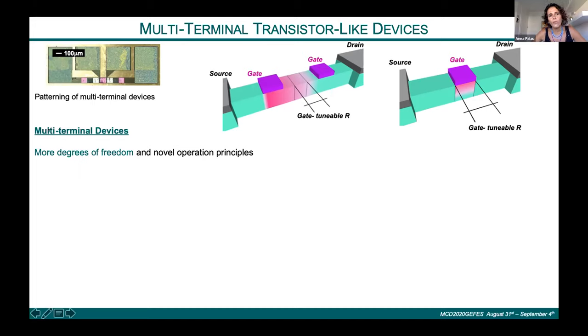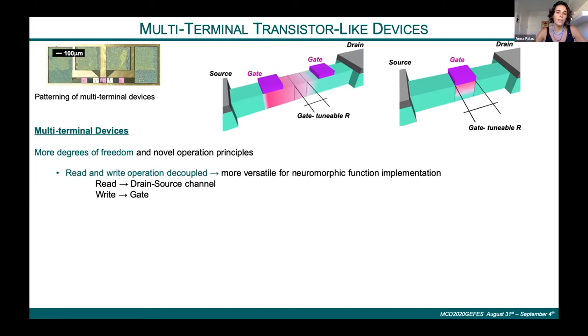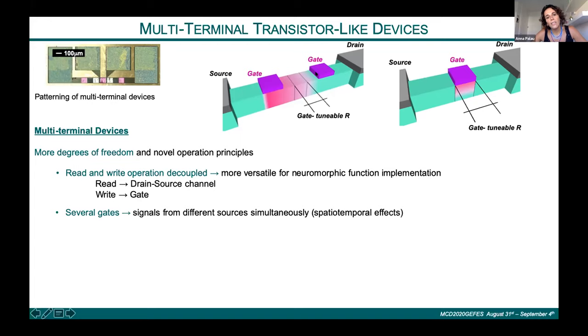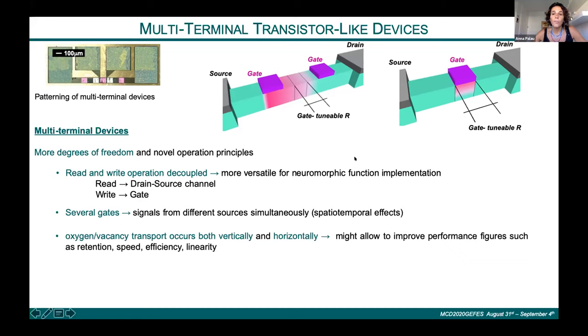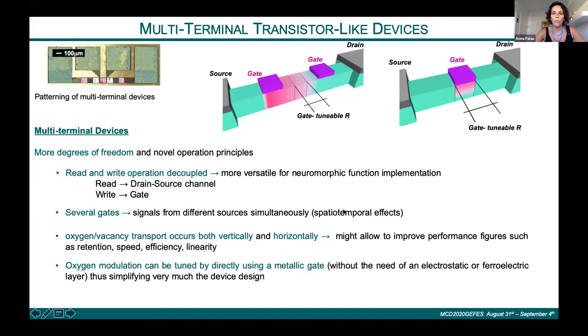By using these multi-terminal devices, we have more degrees of freedom in order to design these devices. For example, we can decouple the read and write operations in these materials. We can use the drain-source to read the state, and we can write the states with a gate. We can also use different gates in the same source-drain system to couple signals from different sources to study spatial-temporal effects. And also, we have the possibility to move the oxygen in a vertical way or in a lateral way, which might allow us to configure or improve the figure of merit of the device that we want to build.